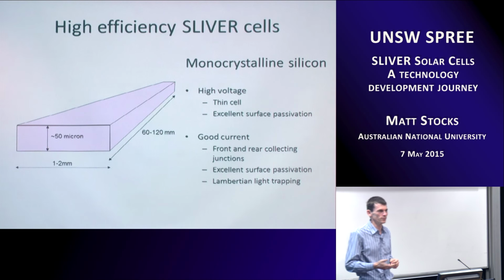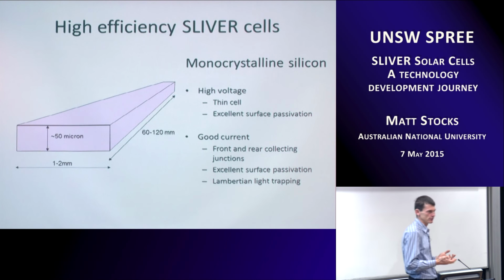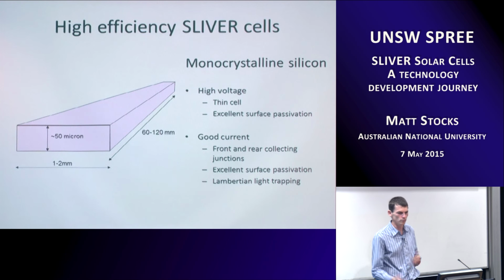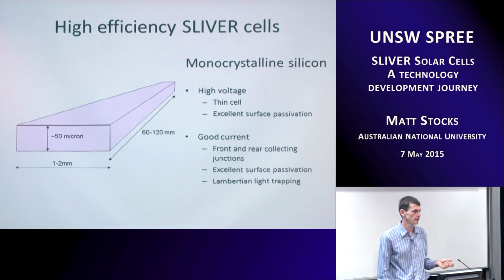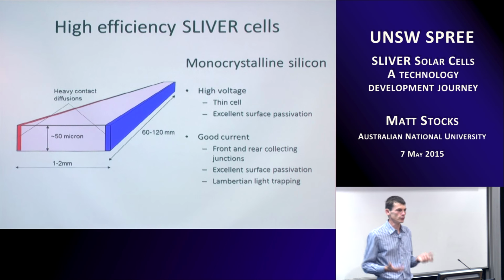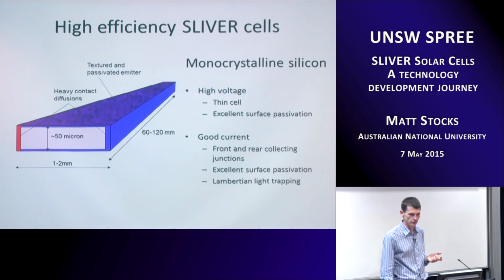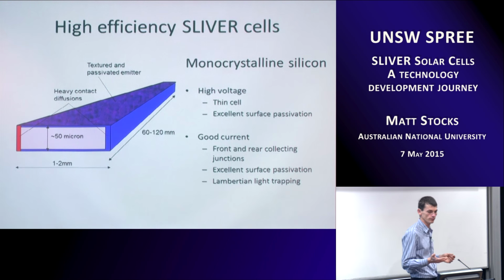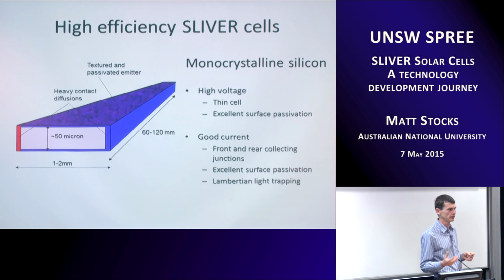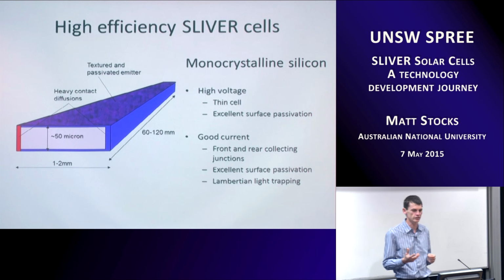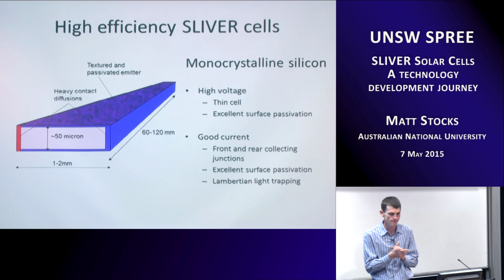The cell design also, because it was a very thin cell and it was made out of single crystal silicon, it was very easy to make good cells. And we were naturally set up to have high voltage because we had a very, very thin cell. And it was also very easy to get very good surface passivation on the surface of our cells. We could do all of our processing in furnaces, LPCVD furnaces, oxidation furnaces, to get our processing down into the grooves of the wafers.